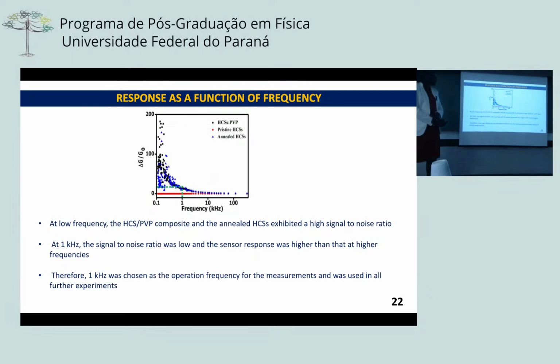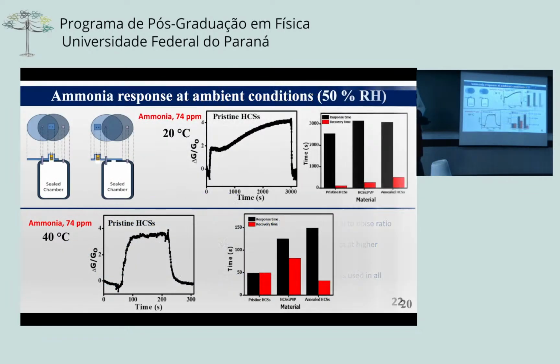The first thing we looked into was the response as a function of frequency, whereby the frequency was varied between 0.1 and 150 kilohertz. From this, we wanted to determine the frequency at which the signal to noise ratio was highest. In this case, we obtained 1 kilohertz, where there is less noise, and therefore we used 1 kilohertz for the rest of the measurements.